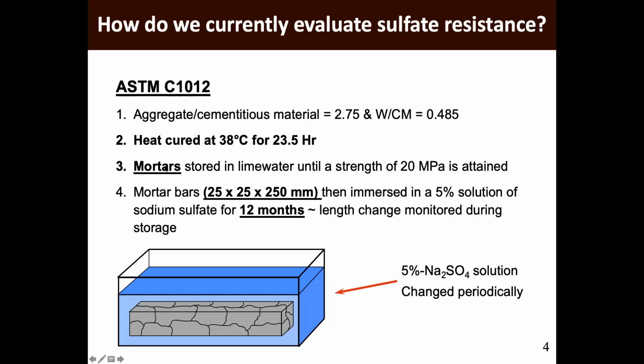Just to give you an idea, that is about 38,000 ppm of sulfate, so it's a very aggressive solution. It's not necessarily uncommon to see these sorts of concentrations in the field, but very rare. Normally we're on the order of about 2,000, maybe 3,000 ppm in a seawater scenario.